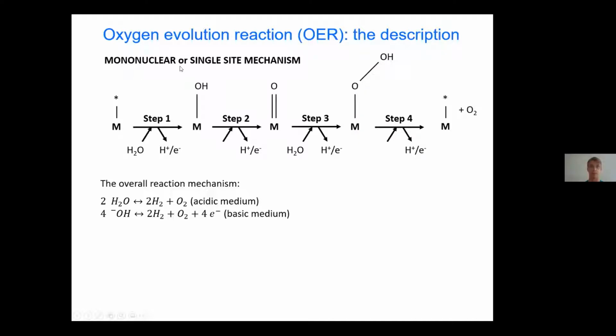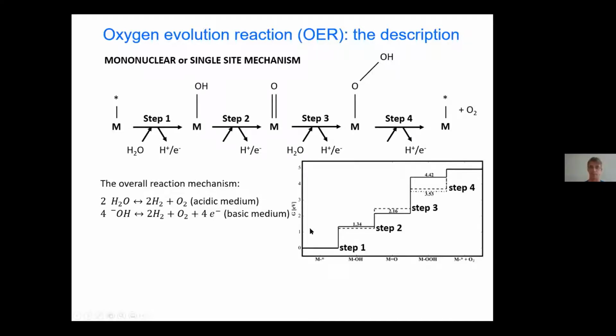We have a mononuclear or single-site mechanism. This means that only one metal or one active site is involved in the catalysis, so everything happens on that catalytic site. If we plot the free energy as a function of the steps, we get what we call an electrochemical step plot, where we see the price we pay for each step, for each proton-electron pair that is ejected when water comes in.